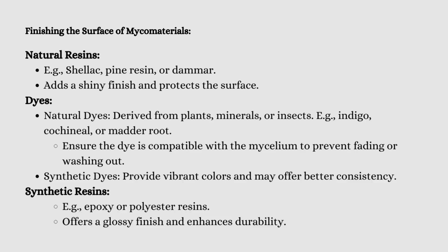Another thing to note that I didn't mention above with the resins is that it's easier to spread these resins if you add a wax. So if you're using pine resin, for instance, you may want to add beeswax, or carnauba wax is a really good one to use with pine resin, so that you can spread it a little bit easier, because it's very tacky. It's so sticky, but it's going to leave almost a caramelized finish on top if you do just the pine resin and alcohol, and it's going to be really difficult to get a smooth finish. So adding a wax really helps.